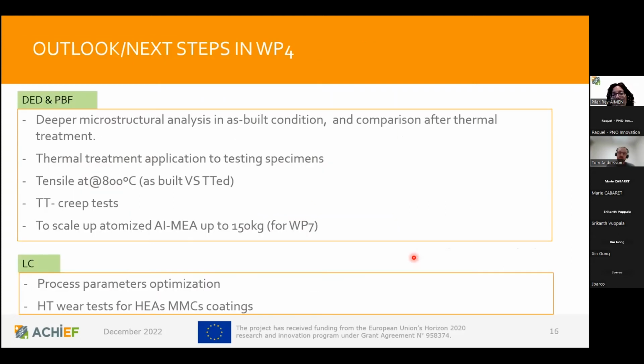So the next steps for this work package is to go in deep and try to understand what is happening in the microstructure in as-built condition, but also to compare with the thermal treated material, and to carry out some tensile tests at high temperature, and to compare as-built with the thermal treated material, and also to develop some creep tests at different temperatures and speeds, and finally to scale up this powder in order to develop the test cases in work package 7.